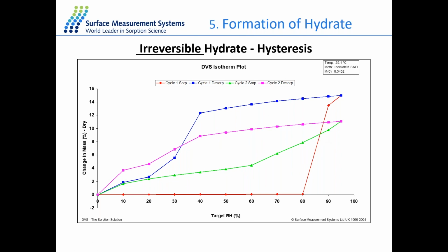So the sample already changed the nature of the material at the end of the first cycle. It's not the same nature as the original sample anymore. And that is because of the irreversible hydrate formation in the sample.